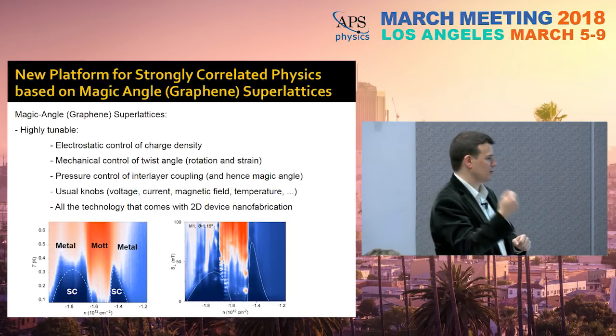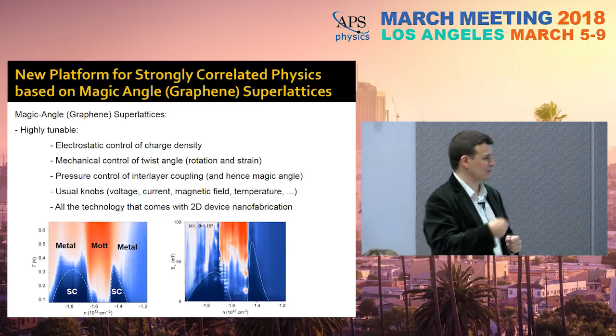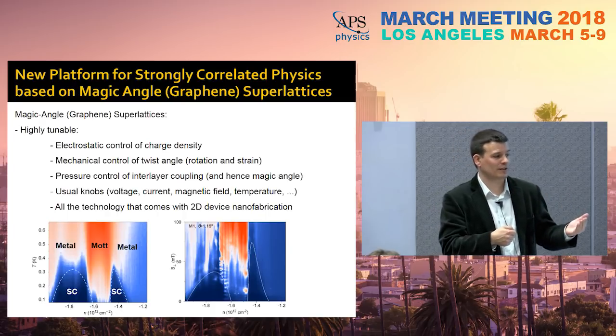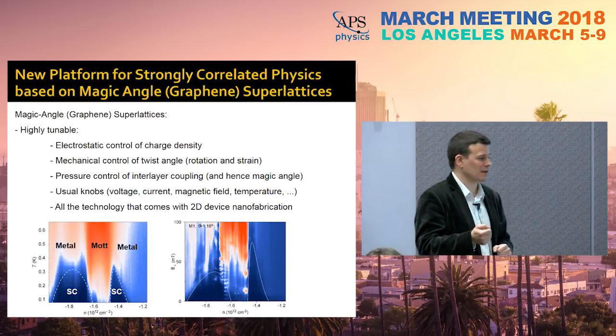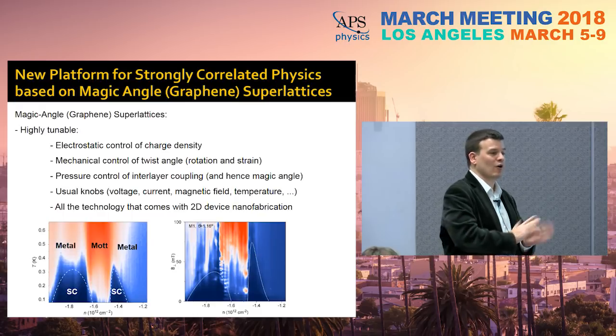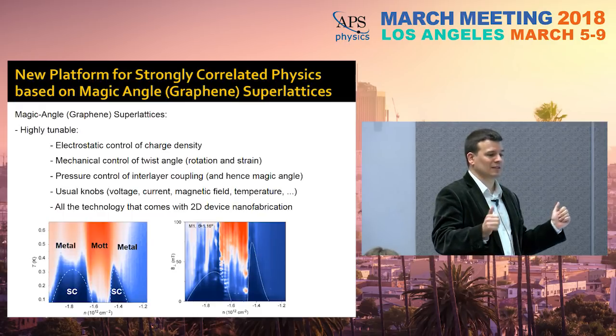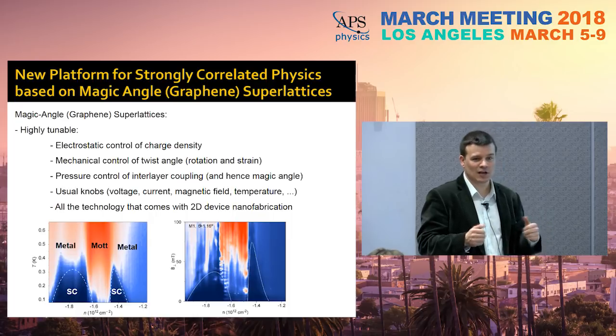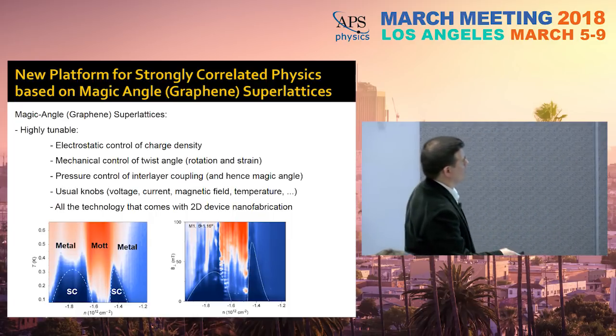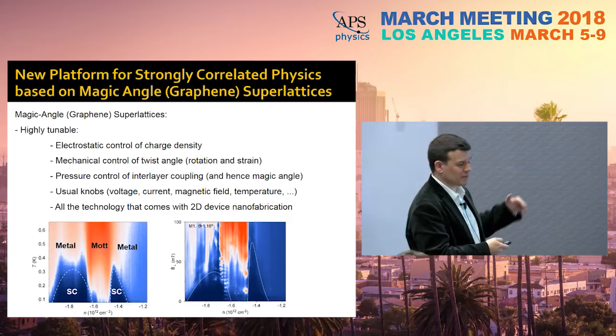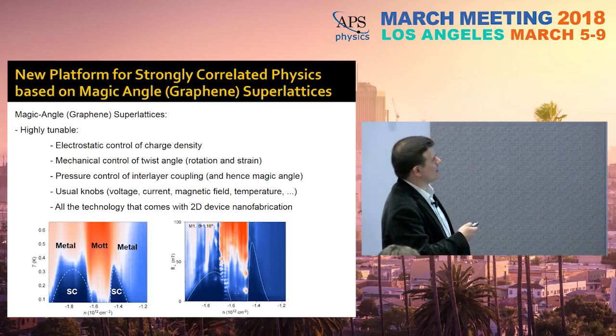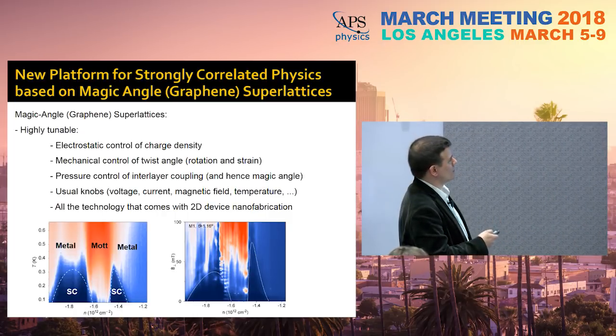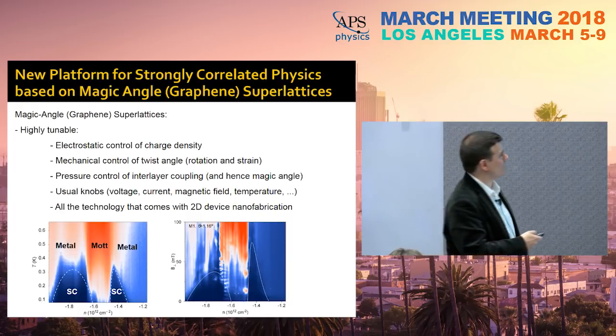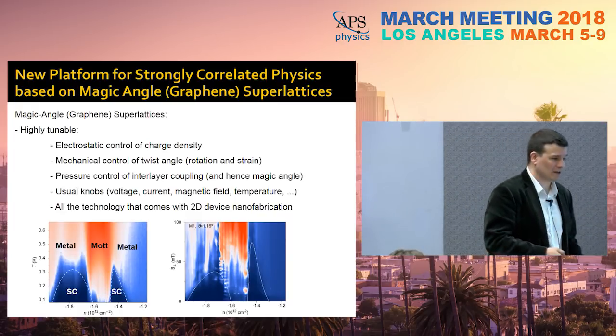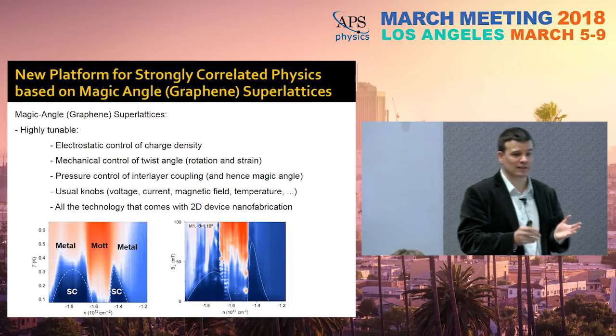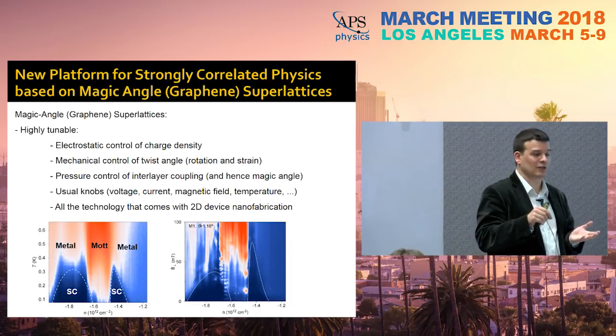If you put materials with high spin-orbit coupling, or 2D materials which are ferromagnets, already superconductors by themselves, quantum spin liquids, topological insulators, there will always be flattening of the bands at a magic angle. There will be enhanced correlations, and you will hopefully be able to study a lot of physics with this. For the particular case of graphene, but for many of the 2D materials it's the same, these platforms are very highly tunable. You have electrostatic control of the charge density. You have mechanical control of the twist angle by rotation, by strain, and in some cases, by some groups like at Columbia, even continuously, possibly.